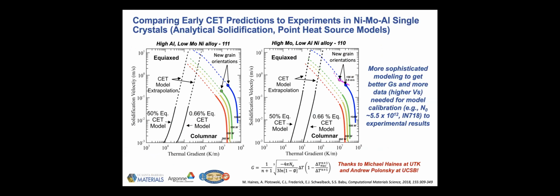So what can we do with this type of information? Some of our early analytical modeling was comparing these columnar to equiax transition predictions to our experiments for these single crystals. These are two different examples of velocity and gradient and these CET predictions for different alloys and different crystal orientations. A couple things became clear to us right away. I should mention too, the colorful parts here are these G-V traces experienced in the melt pool for the different power conditions. And then these are our CET extrapolations.